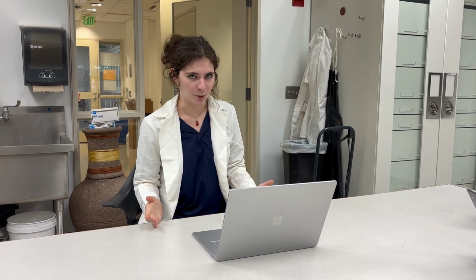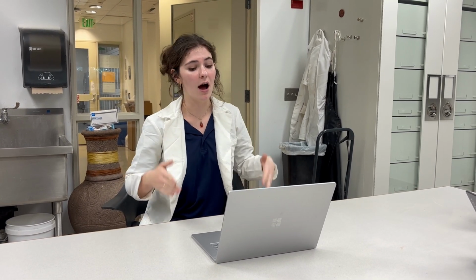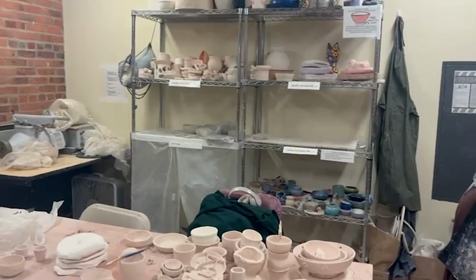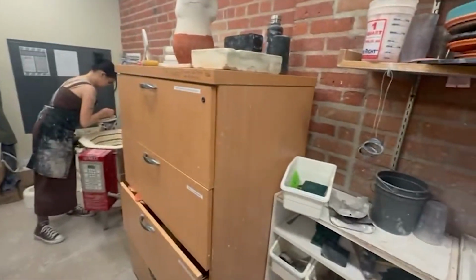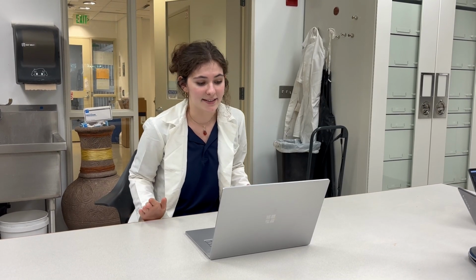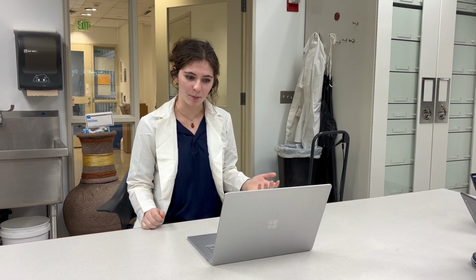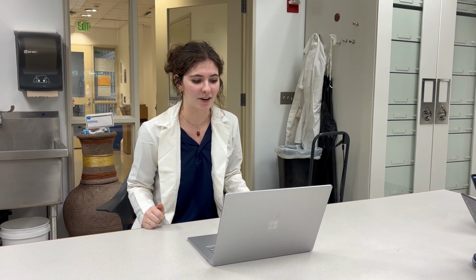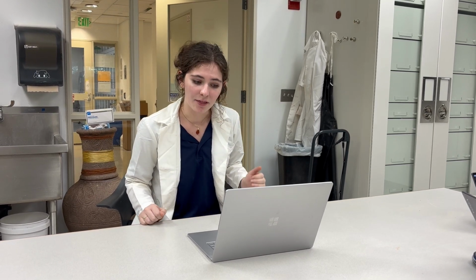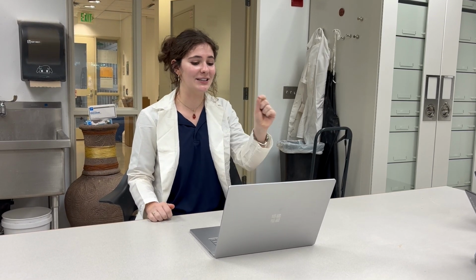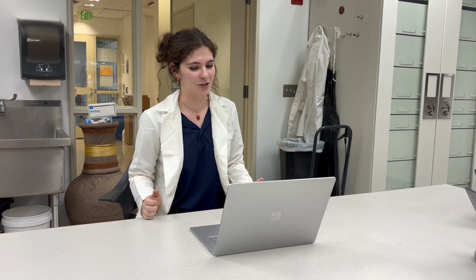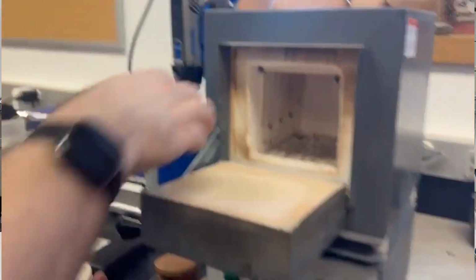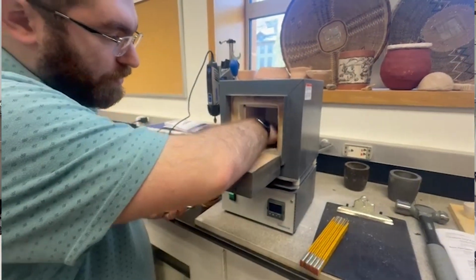In determining at what temperature to fire our clays, we were a little at the disposal of the most accessible kiln that we had. We used the Skutt electric kiln in Pearson College to fire our discs, and because their kiln is used by other students as well, we simply had to fire the ceramics at the temperatures that the Pearson kiln offers. The first temperature was the temperature at which glazed pottery is fired, at 6 cone, or about 2230 degrees Fahrenheit. The second was the temperature at which bisque clays, or clays without glaze, are fired, at 0.06 cone, equal to about 1816 degrees Fahrenheit. We tried to fire a third group at another temperature, but we ran into some issues with that.